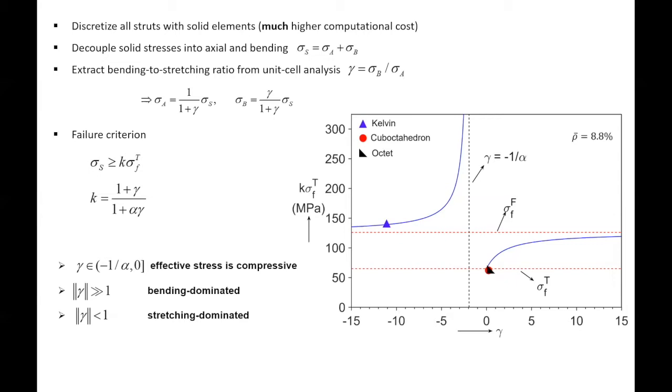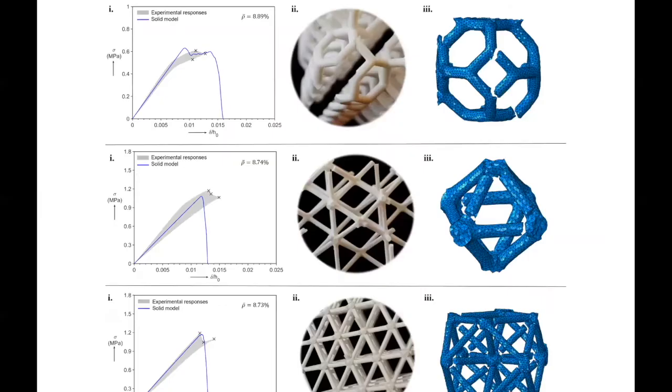All right, so we had all of this, and now we're feeling pretty good about it. So now we go back to the solid model. These are just extracted units. It's the full finite size domain. And now, as you can see, the solid model was able to capture all the experiments. And not only that, we even looked at exactly the mode of failure, where does it fail and how does it propagate, and we're very happy with seeing very close similarities between the failure patterns in experiments and models.